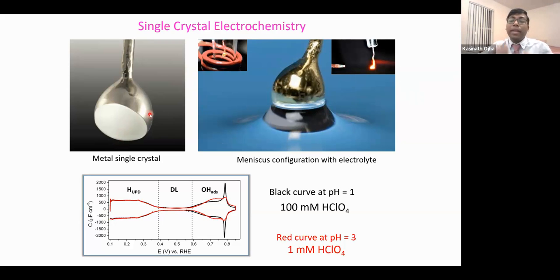So we basically melt the high pure platinum metal and slowly cool it down to room temperature. Like zone refining? Yeah, sort of. If you do that, then it crystallizes, and then you have different facets. So what is the guarantee that this particular facet will be exposed?